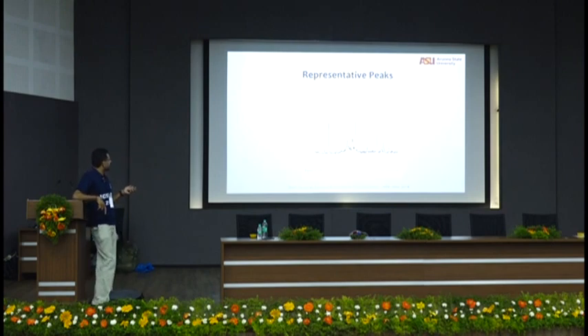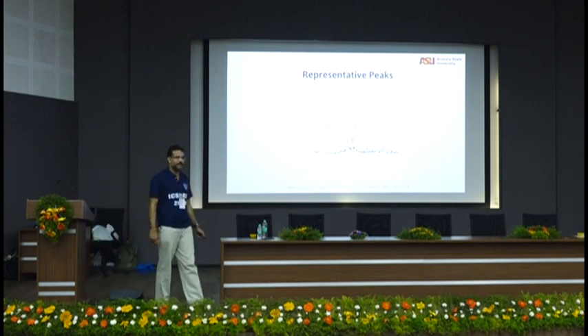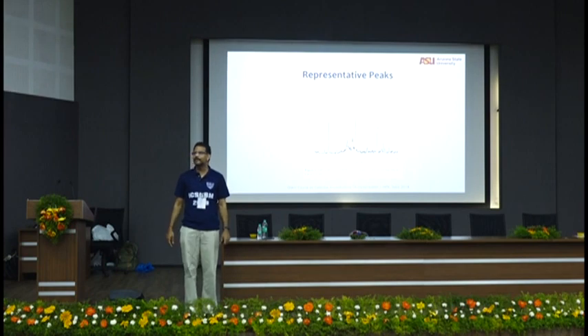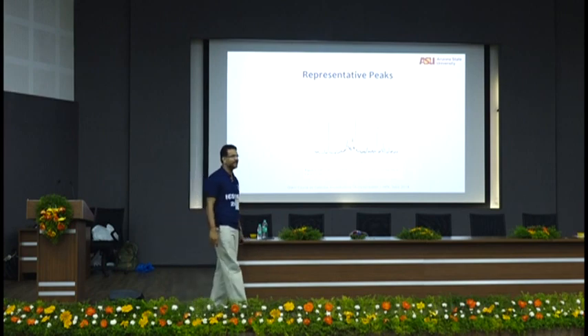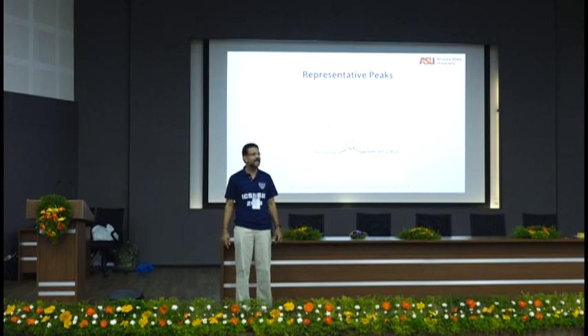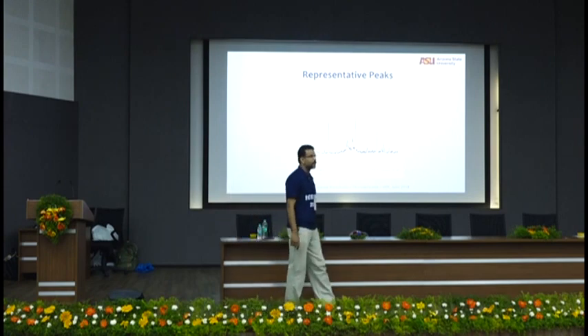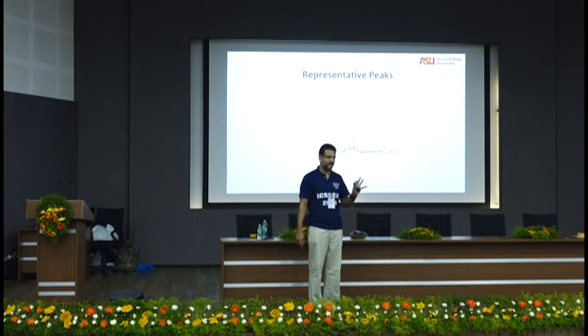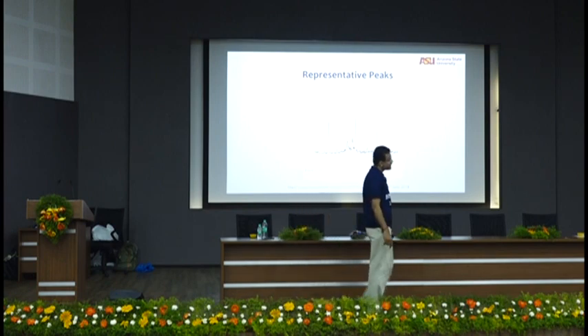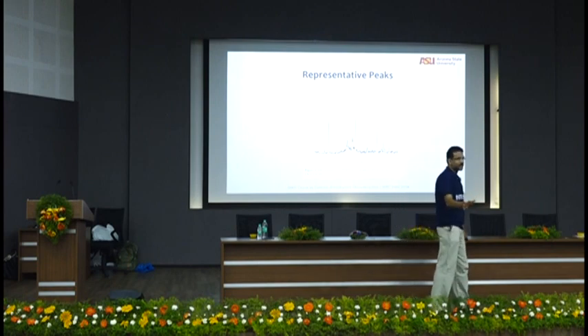Okay, so representative peaks in a hydrated cement paste, 28 days hydrated cement paste. Calcium hydroxide, you will always get this beautifully. Why? Calcium hydroxide is a real crystal. You will get calcium hydroxide really, really nicely. And if you do a pure cement paste, that is the only thing that you can guarantee that you have in your system based on XRD. That is it. If you have put in limestone, you will get calcium carbonate peaks that you can guarantee. If your gypsum has not reacted, you will get gypsum peaks that you can guarantee.